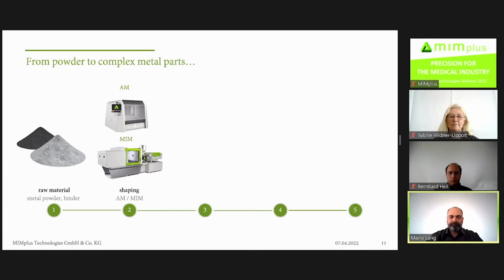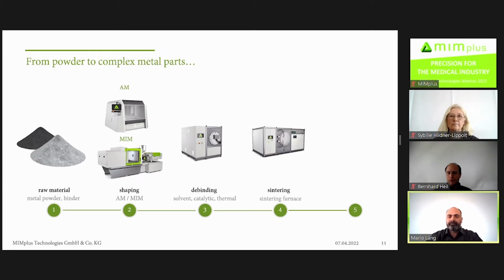So one, the more older thing is the MIM. That's the shaping by an injection molding machine, which is quite well known. And the more newer technology is the AM or additive manufacturing technologies, where we have different ways to form the parts in-house. After shaping the so-called green part, you have a debinding process. That means you remove most of the binder and leave the metal powder in the part. And after that, you do the sintering process, which forms out of the powder a complete metal part.